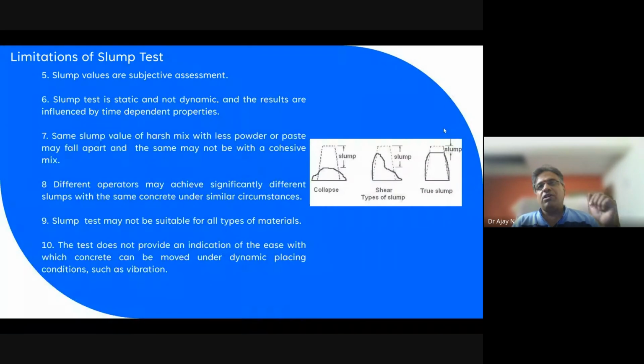In a general sense, we can say that the slump is a more subjective assessment. As I said, the slump is more relevant for the formwork placement of the concrete, spreading the concrete on the formwork, tapping. The same thing we are simulating with the slump also, but here we are not taking into account the pumping effect, which is a dynamic effect. And also when we introduce more powder, or when we introduce an SP or superplasticizer, it is not giving an indication, and it is not giving a proper differentiation between which mix is better.